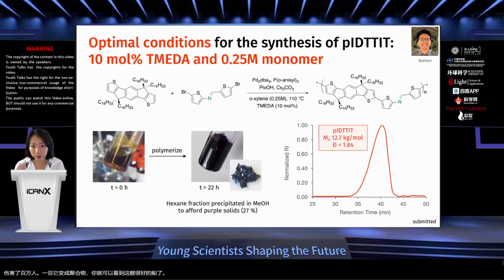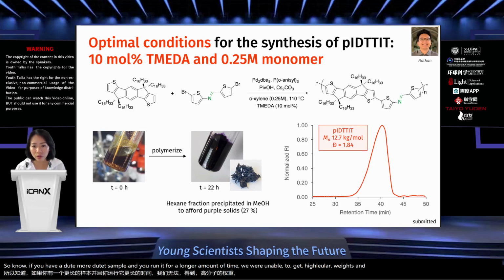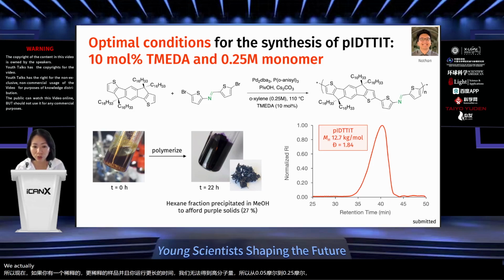Now, in this polymer system, another handle that we looked into was actually concentration. So, if you have a more dilute sample and you run it for a longer amount of time, we were unable to get high molecular weights. And so going from 0.05 molar up to 0.25 molar, we actually saw much more consistent results in yields as well.